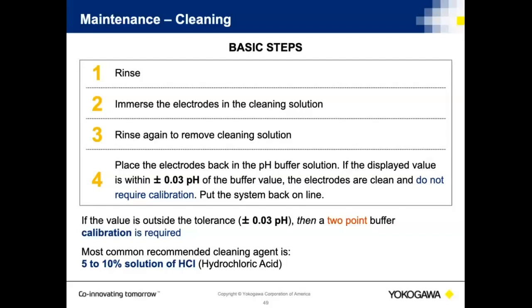The key is, sometimes what I see is people are calibrating too often. If you do a calibration check or a validation check that just says, let me check my pH probes in buffer solutions, and let me do it weekly, and there's no difference greater than, say, plus or minus 0.03 pH units, then don't calibrate. Put them back into the system and just let it run. The reason I say I see people calibrate too often is when you calibrate too often, you have a tendency to hide problems that are starting to establish themselves with the pH electrodes.